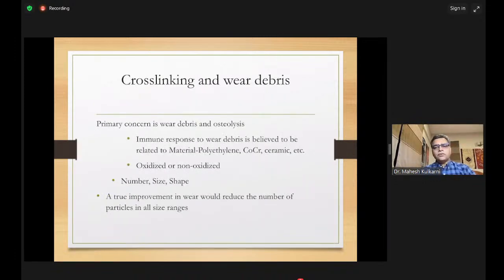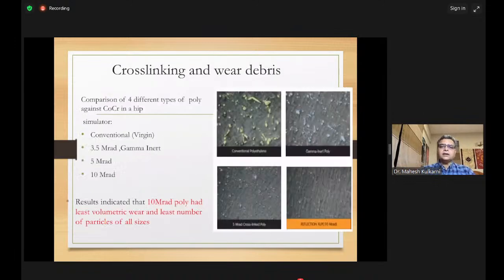Now, why do we talk about cross-linking? The primary concern obviously is wear debris and osteolysis. And we're worried about the immune response to this wear debris, and the particle size, shape, everything matters for it to stimulate osteoclasts and cause bone resorption. So we should not only think about cross-linking of the poly, but we should also think about reducing the number of particles which are generated.